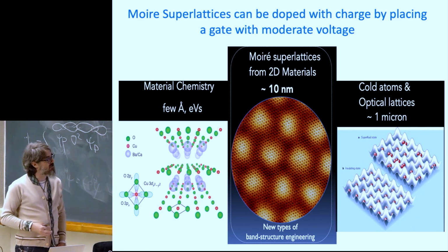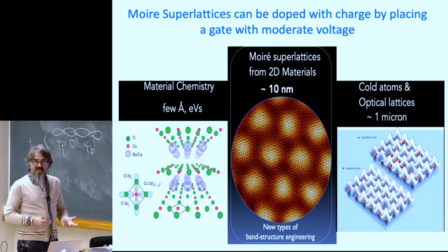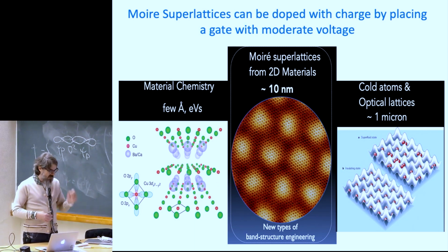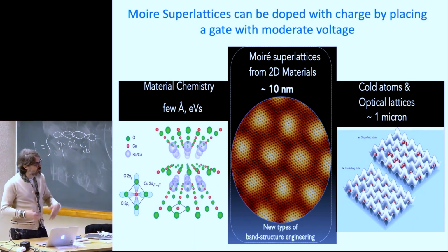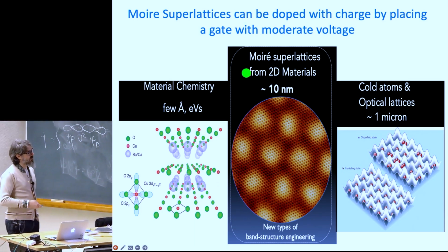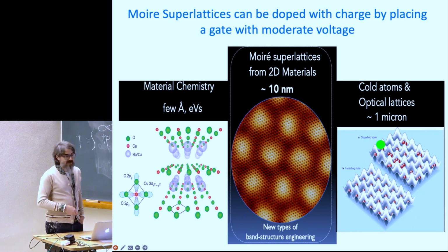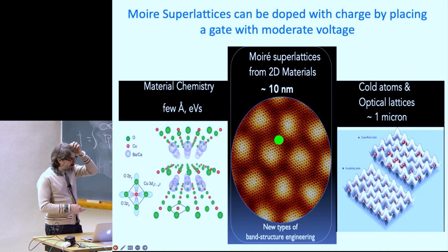The disadvantages are the length scales and the fact that you're going to have much less density of electrons than in a material chemistry situation. The advantage is controllability and doping that you can do without adding impurities. So this is a Moire lattice, which is just a twisted layer, 2 layers of graphene, for example, in this case.